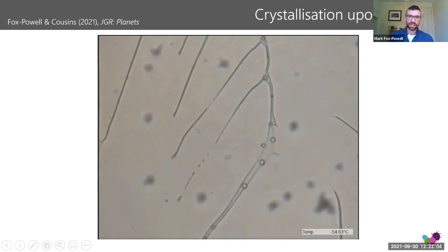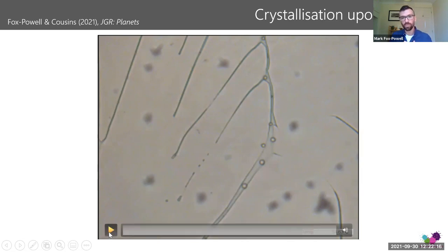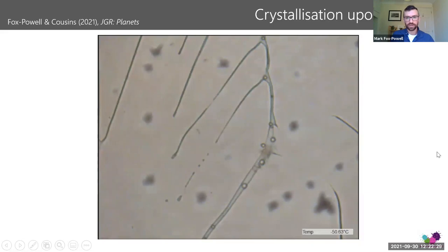What you're looking at here is primarily ice, but you can see one of these brine veins through the middle of the image. There's a few bubbles of gas suspended in it that have formed as it went through a glass transition. And as you rewarm this, what you'll see is a yellow crystal mass nucleate around here where my cursor is, and spread throughout that brine vein. I'm playing it now, and you can see that crystal mass forming. This is happening at temperatures far below the melting point of the system. So this is a recrystallization, a reordering of that glass upon warming.